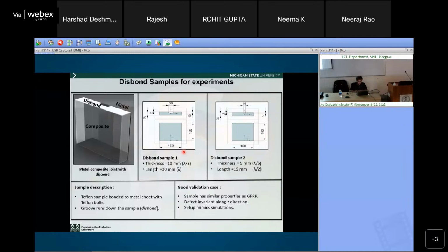So we were talking about the experimental validation of time reversal imaging. This is the same sample. We have a groove that is all the way down, and you have a metal backing at the other side. So this is your composite sample. This is a defect, a disbond, and on the other side there's a metal backing. The thickness of the sample in terms of wavelength is lambda by 3. The length is 1 lambda, and the disbond is lambda by 6. It's really sub-wavelength.